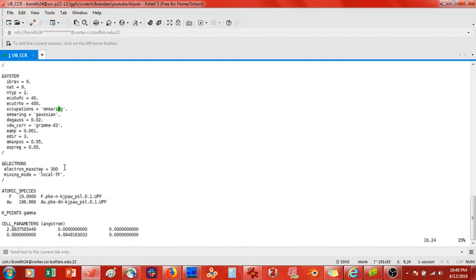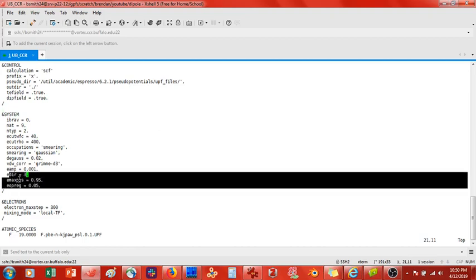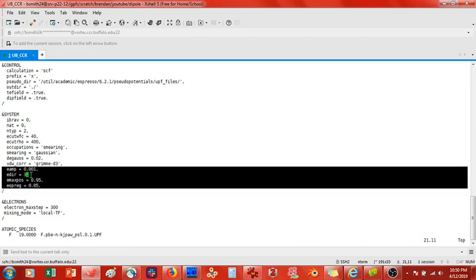What I would then do is I would do a variable cell relaxation process, which I also don't do here, but I'm just telling you what other steps you need to do in addition to what I'm doing here. Well, let's say I've done all that. I have my optimal nuclear geometries. I've converged with all my electronic structure parameters. Now I want to apply the dipole. So what I've done is I've added the tefield and dipfield to the control namelist, and I've added these four parameters to the systems namelist. And what we're going to do now is we are going to just exit out.